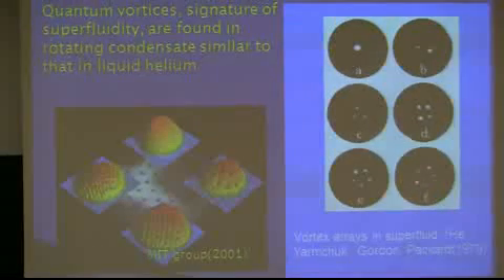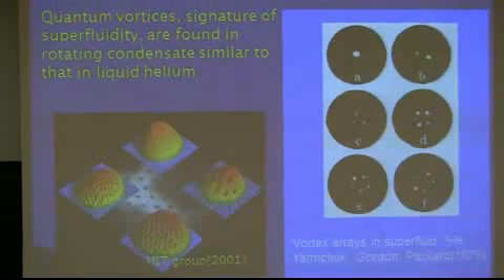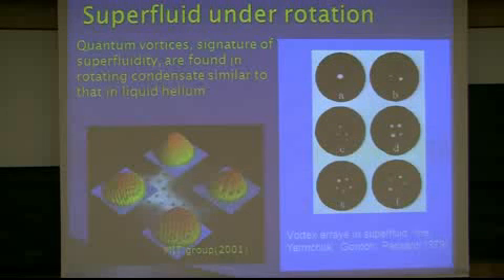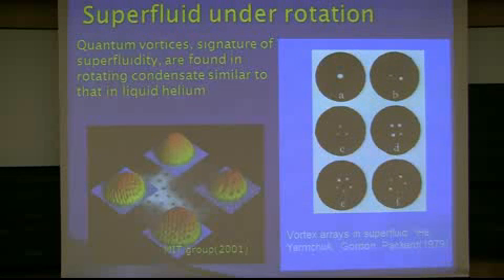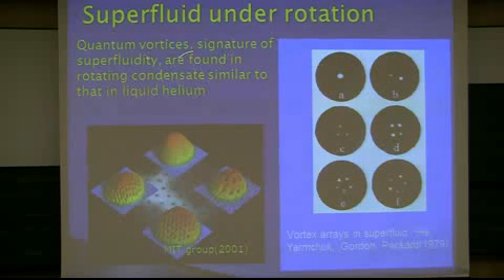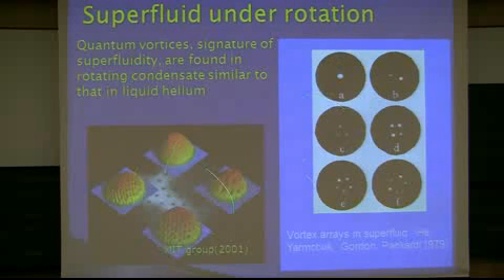However, the story is completely different when you have a superfluid. Even with very slow rotation, you can destroy the phase coherence of the superfluid. Because of the destruction of phase coherence, vortex cores appear, which are non-superfluid, in the superfluid system. These quantized vortices were imaged earlier in liquid helium and also in Bose-condensed alkali gases. So this is the density profile of a Bose-condensed alkali gas.